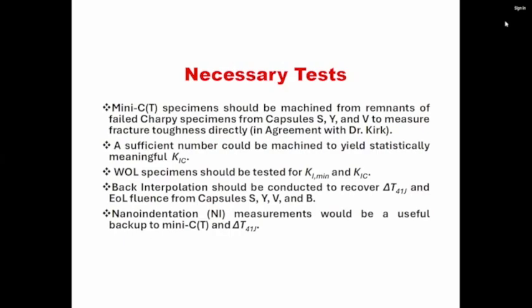The necessary tests: I don't disagree with everything that Dr. Kirk says. The one thing we do agree on is that Mini-C(T) specimens should be machined from remnants of the failed Charpy specimens from capsules S, Y, and V to measure the fracture toughness directly. A sufficient number could be machined to yield statistically meaningful values for the fracture toughness. The WOL specimens should be tested for both K1 minimum, that is, the crack would grow until the stress intensity factor becomes limiting at its lower end and the crack stops growing, and then it could be loaded in a load frame and pulled to failure in order to calculate K1C, the fracture toughness, from compliance of the specimen.